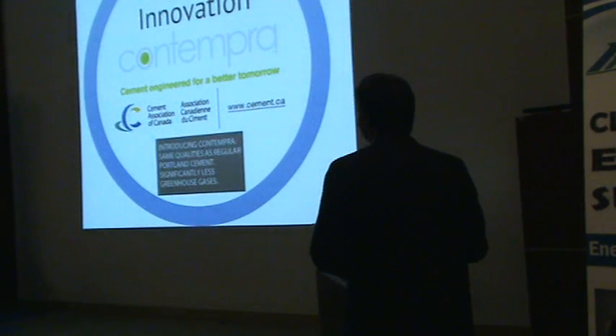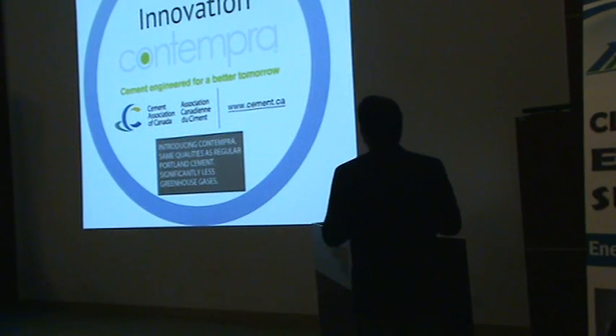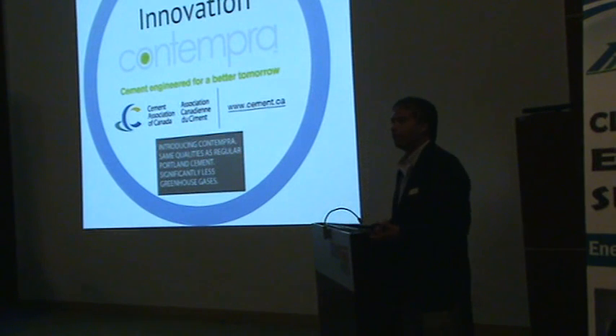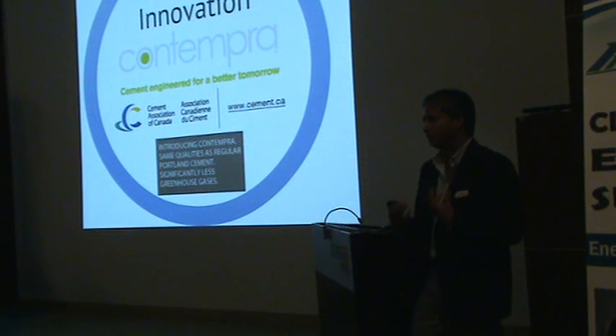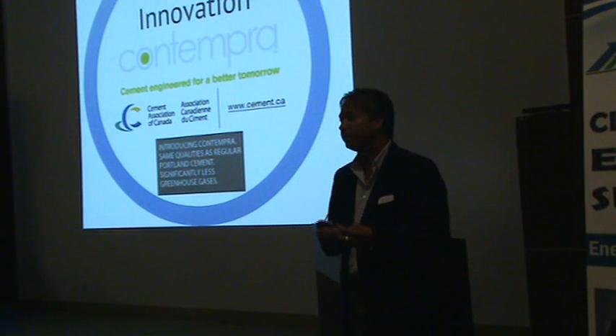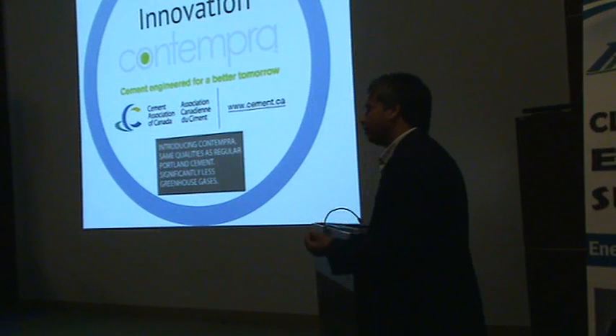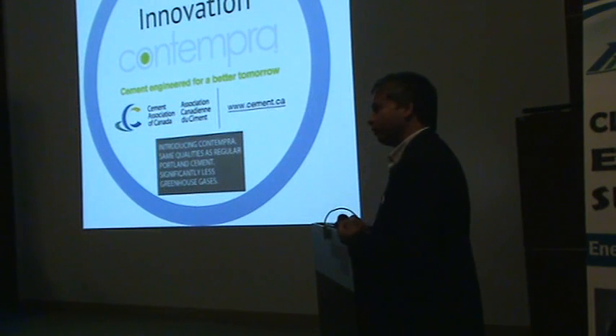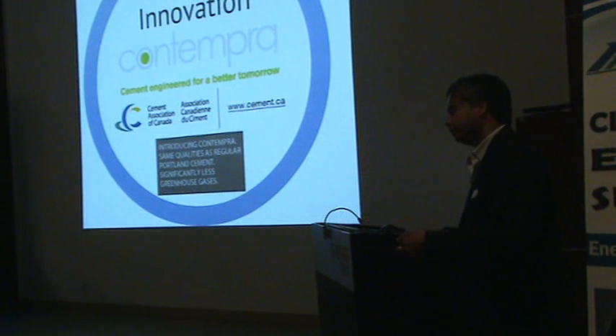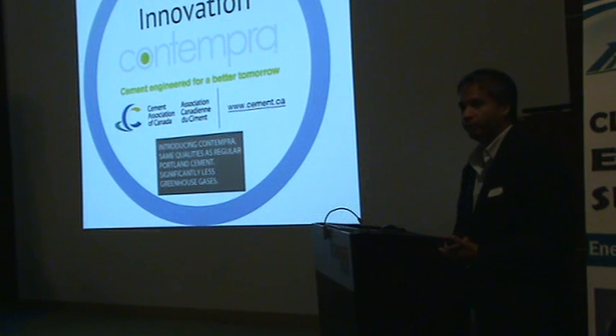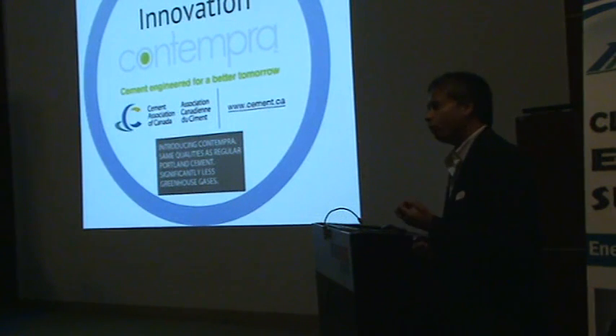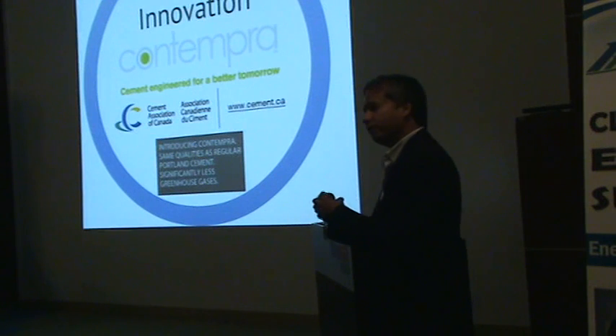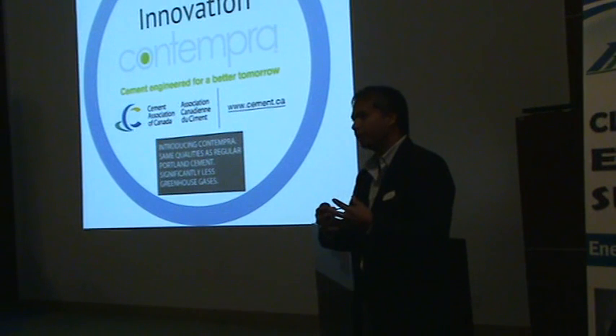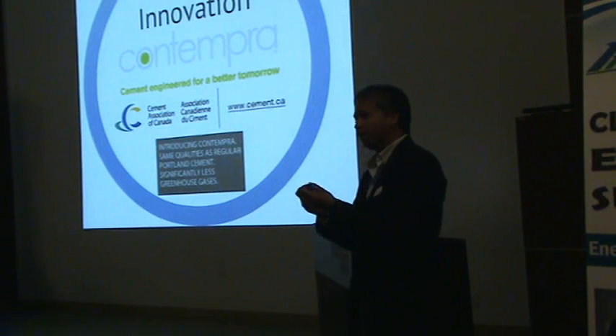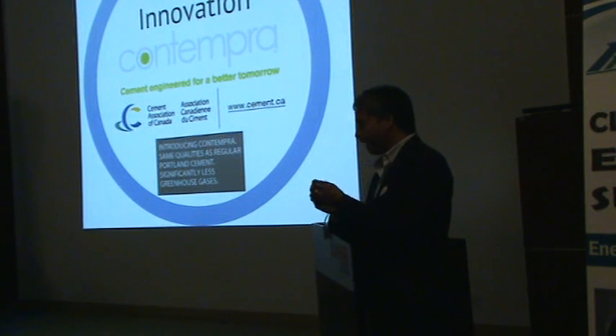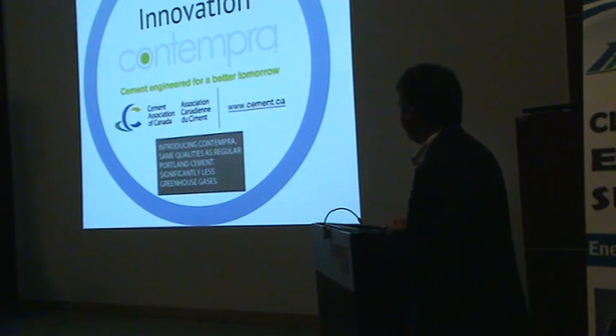Product innovation. The industry got together to develop together a new cement standard that we are actively pushing and marketing, which contains about 10 to 15% interground limestone in the cement product. That reduces the amount of material that has to go through the kiln by 15%, which reduces greenhouse gases by 15%. And though it might weaken the glue effect of the cement, it actually increases the strength equivalently by having microfine sand particles. So that microfine aggregate that you put in offsets any dilution factors.